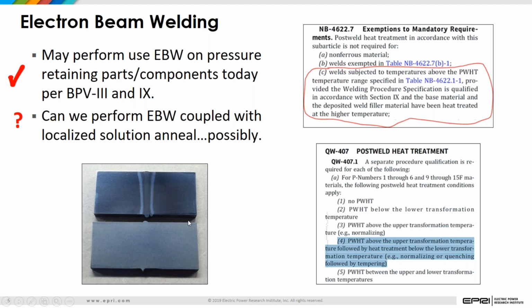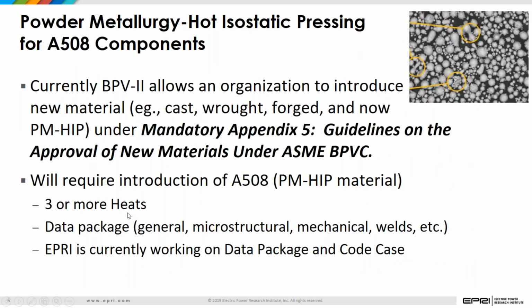So the question is, can we utilize this to minimize or reduce the number of inspections that are performed in service? Clearly, you'll have to do a fabrication inspection, but could you do that as an in-service inspection? So later on, or eliminate some of those in-service inspections. Some of the information that's shown on the right-hand side of the screen, I'm not going to go into this, but it does allow you to address post-weld heat treatment issues in a slightly different manner than what we might look at for a stress relief, which is what we utilize today.